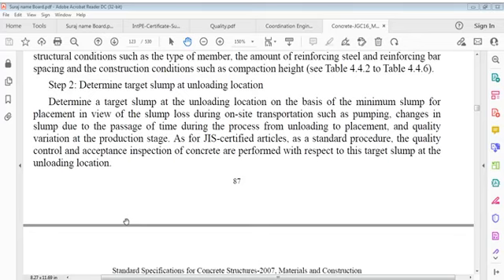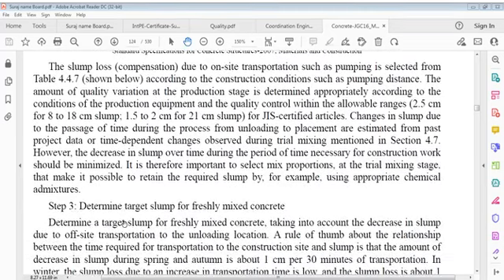As for this standard, as standard procedure, quality control and acceptance inspection of concrete are performed with respect to this target slump at the unloading location. Slump loss, and we can say compensation. Slump loss due to on-site transportation, such as pumping, is selected from the given table according to construction conditions, such as pumping distance. The amount of quality variation at the production stage is determined appropriately according to conditions of production equipment and quality control within allowable ranges: 2.5 centimeter for 8 to 18 centimeter slump, and 1.5 to 2 centimeter for 21 centimeter slump.